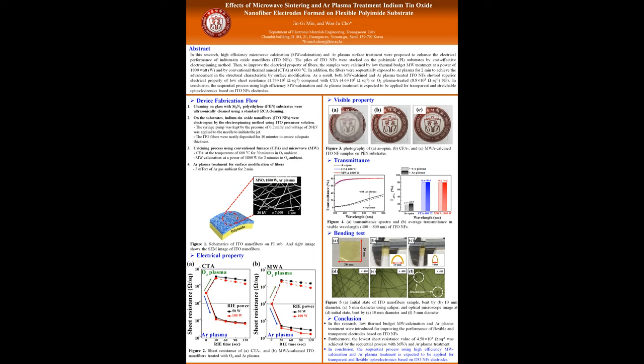To see the transparency of the device, nanofibers were electrospun on PEN substrate, and then furnace and microwave treatments were applied respectively. As a result, the heat-treated device was found to have a much higher transmittance than the initial state device. Furthermore, the flexibility of the device was checked through the bending test. As a result, it was confirmed that there was no damage on the nanofibers even when bending the sample up to 10 mm.